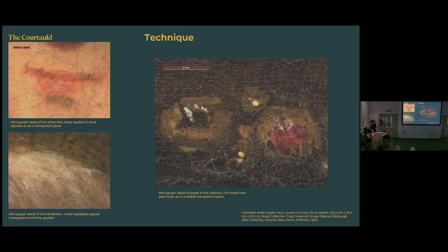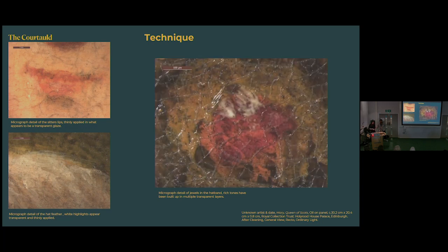This is especially evident in the jewel here, which is in Mary's hatband, where this cherry red transparent layer appears to have been applied over a more opaque orangey layer beneath, and then finished with a semi-transparent white highlight, which has been added in what appears to be the final stages of painting, and that is quite common throughout the whole of the composition. It's fairly similar in the detail of the hat feather there as well. The white highlights do appear to be added last and over the green background as well.